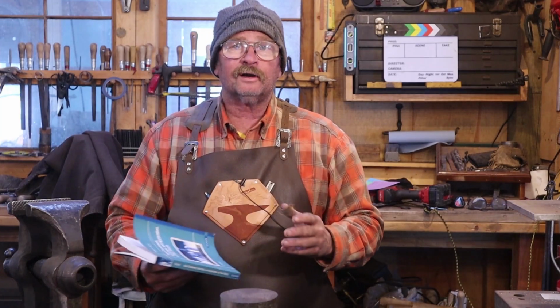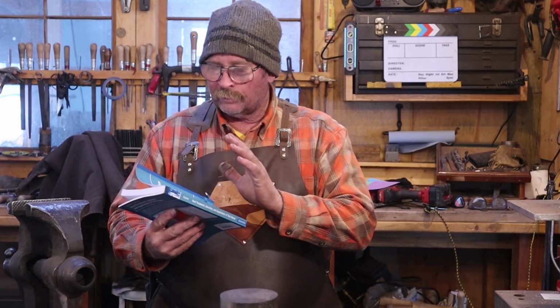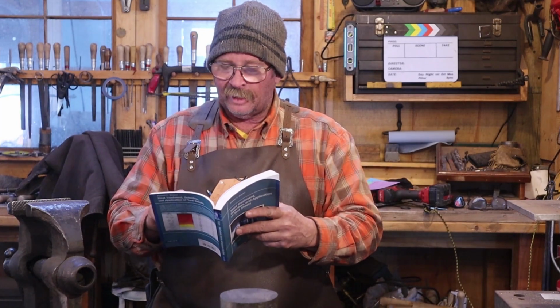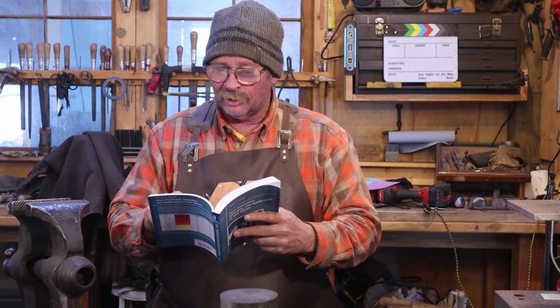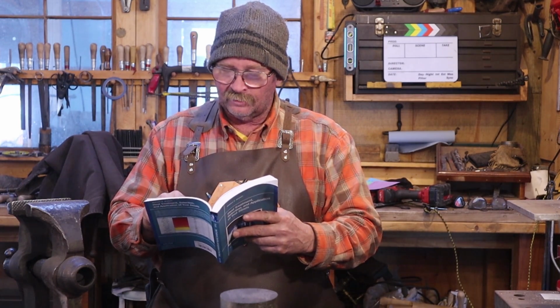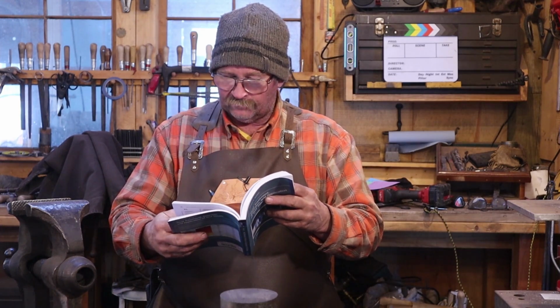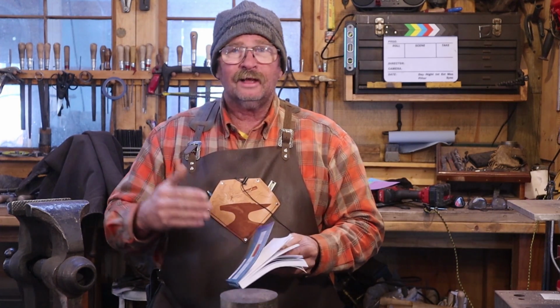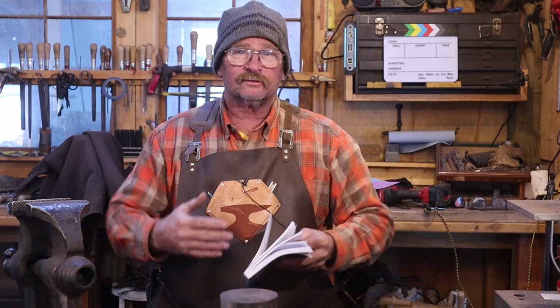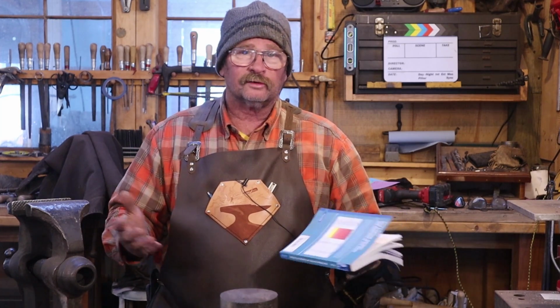Now somebody out there is wondering what hardness this is going to be. Now according to Bryson's Heat Treatment and Application of Tool Steels, they have a tempering chart that I go by, and it says at 450 degrees, it's going to be about a Rockwell 58. That's a good hard hammer, not as hard as a wood chisel or something like that. But for a hammer, that is plenty hard. They just don't need to be all that hard, especially when you're forging hot steel with them because the hot steel doesn't hurt the hammer.